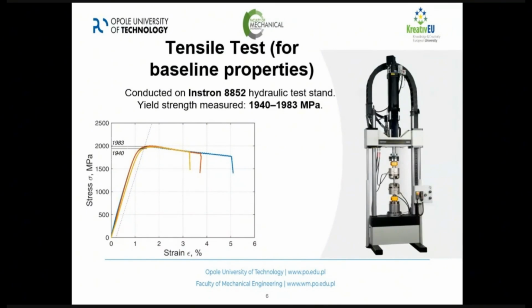As a start, we did some tensile tests, 3 specimens in this case, on the hydraulic machine from Instron, and you can see the results on the slide here. The yield strength changes from 1,940 to 1,983 megapascals, so the results were quite close, and you can see that the material is, let's say, elastic brittle